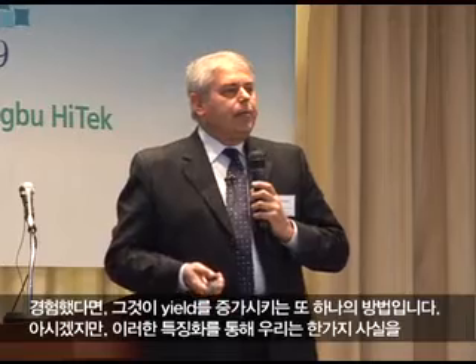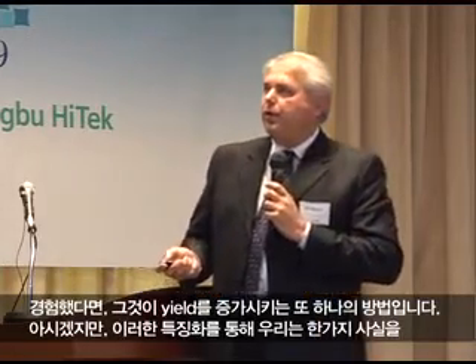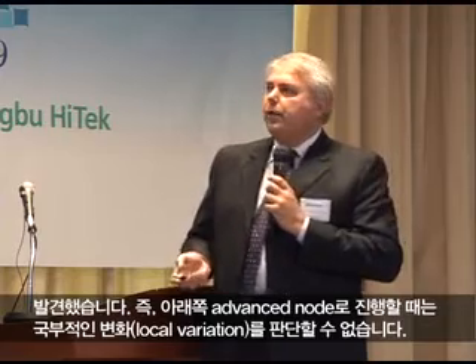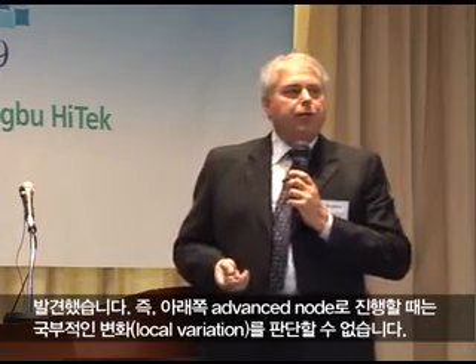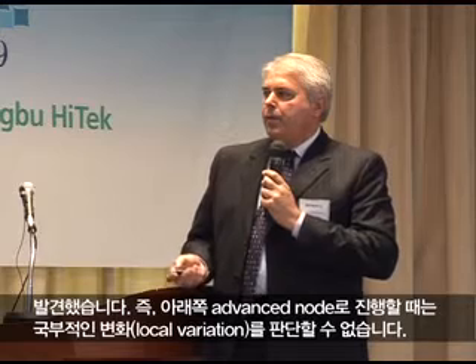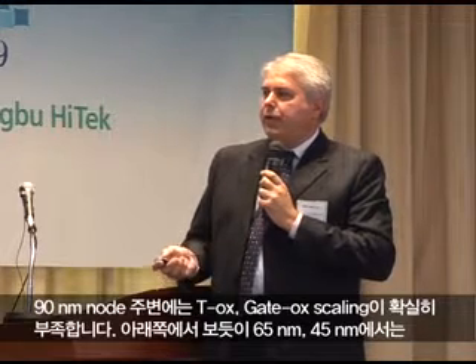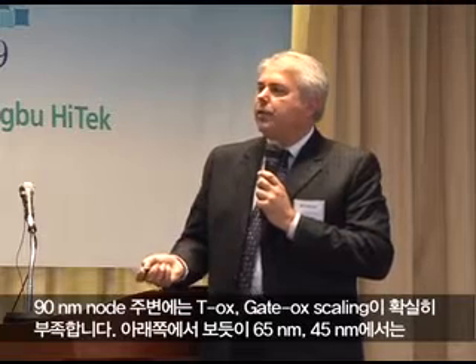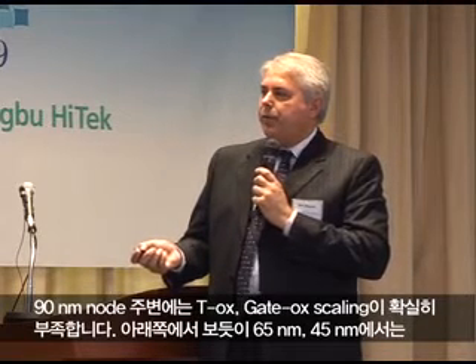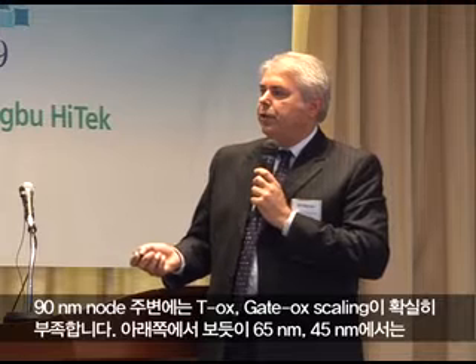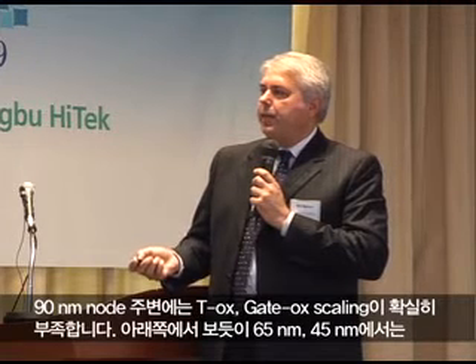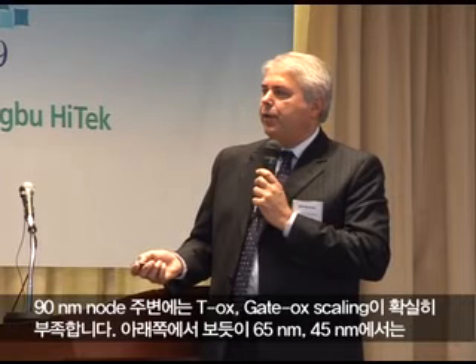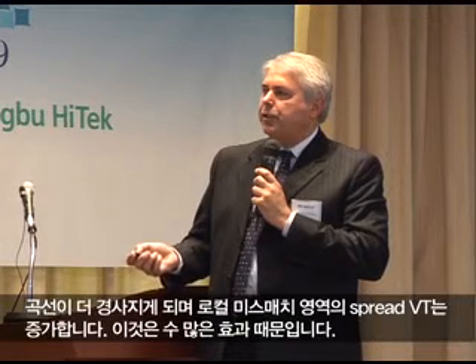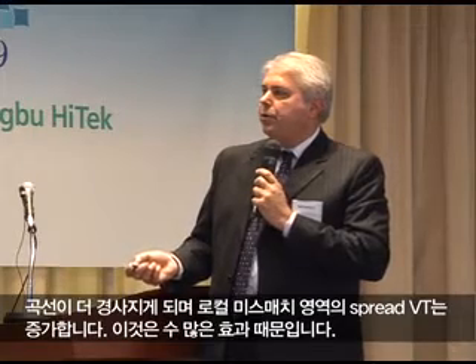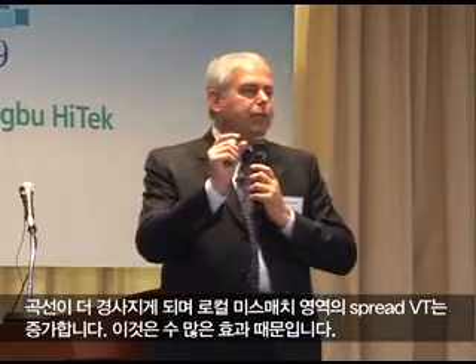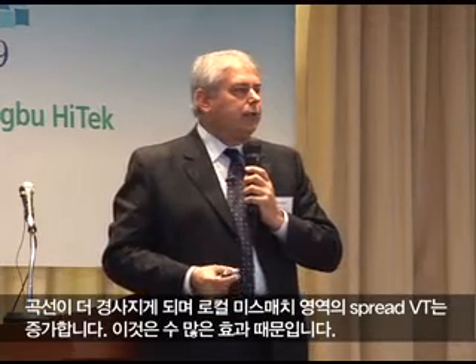Through these characterizations, we found one thing, and I think this is also known, that local variation does not scale as we go down into the advanced nodes. There's a lack of TOX gate oxide scaling that's evident like around the 90 nanometer node. And you can see as you go down in the Moore's Law curve here, 65 nanometer, 45 nanometer, actually your distribution, your spread of the VT in the local mismatch area becomes increased.